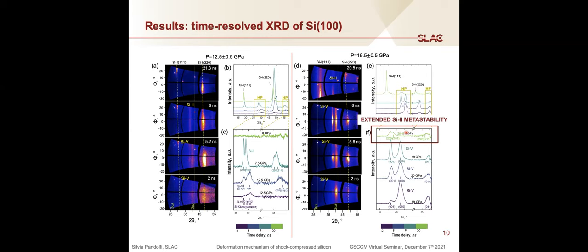And another aspect that is very interesting of these results and that I'd like to stress is that we observe a very reproducible texture evolution for which the peaks of the high pressure phase seem to be growing in intensity, but also in azimuthal extension. So it seems like texture is developing with time.